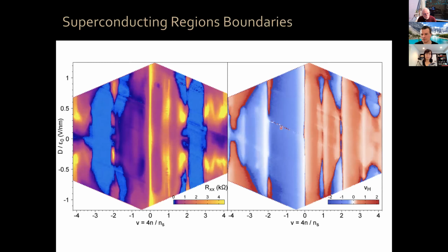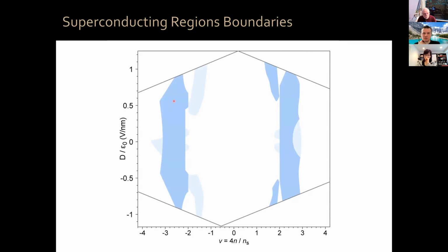Okay, so now we have these two phase diagrams, for the resistivity and for the Hall density, and we can try to see if anything is correlated between these two phase diagrams. Okay, now because superimposing them would be too complex, I'm just going to superimpose schematically these two phase diagrams. So what I'm going to do is I plotted here the superconducting regions, as a function of filling factor and displacement field. Okay, dark blue means robust, strong superconductivity. Light blue means weak superconductivity, still present but weaker.